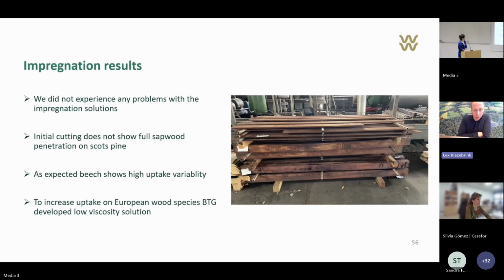Well, that's actually what I already told. One thing I didn't mention is that in order to increase the uptake on European wood species, for example this pine, BTG also developed a low viscosity resin, and we're currently still impregnating with this solution to see if it improves the uptake.